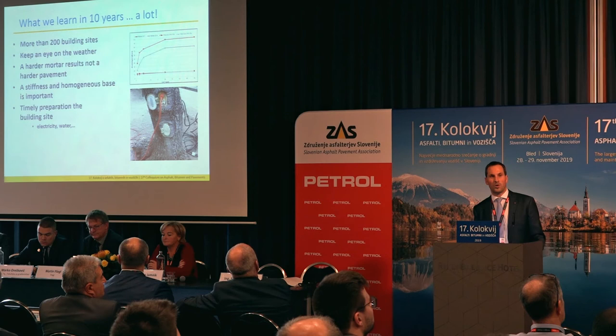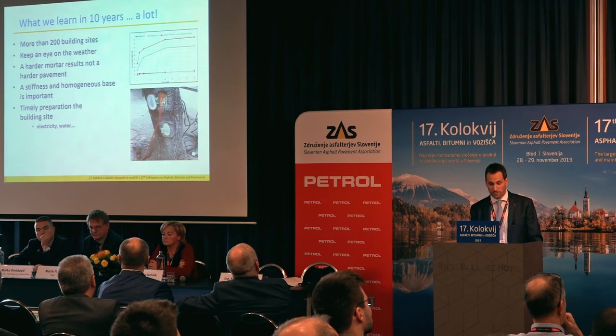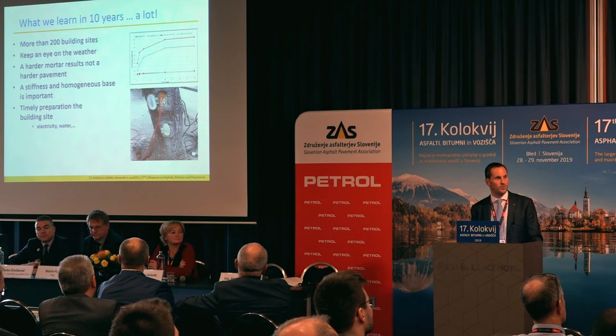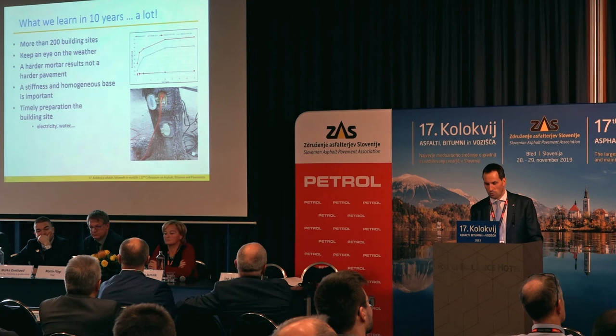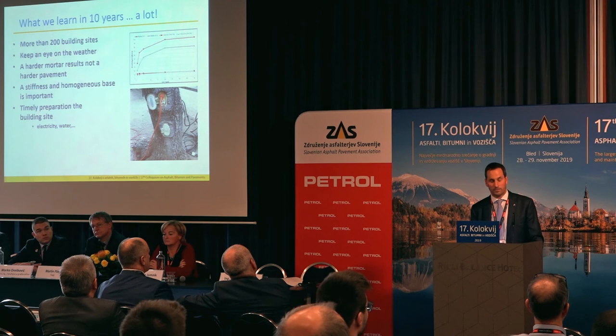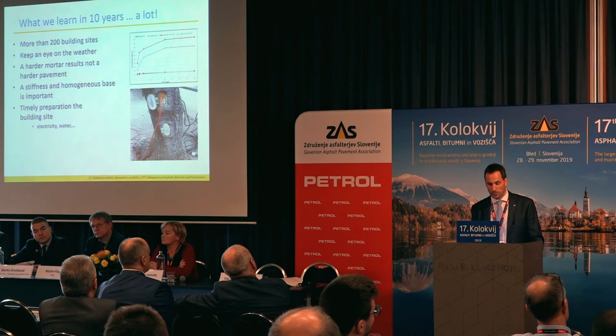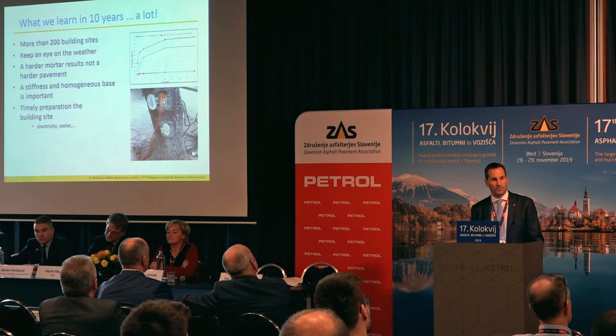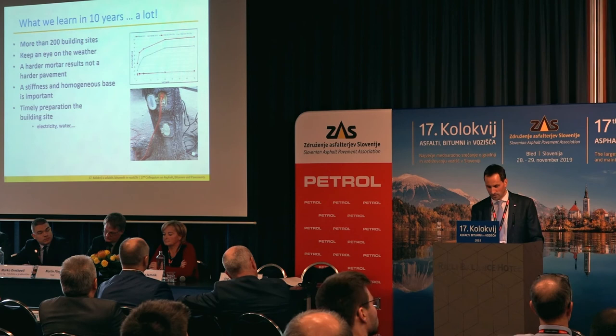What we have learned after 10 years of experience with our mortar and the construction of semi-rigid pavement is a lot. We built more than 200 building sites in Austria. It was very important to keep an eye on the weather. A harder mortar does not result in a harder pavement — we made tests in our laboratories with mortars of very high strength, but there are no different results at the end in the layer. A stiff and homogeneous base is very important, as is timely preparation of the building site: have electricity there, have enough water there with enough water pressure.